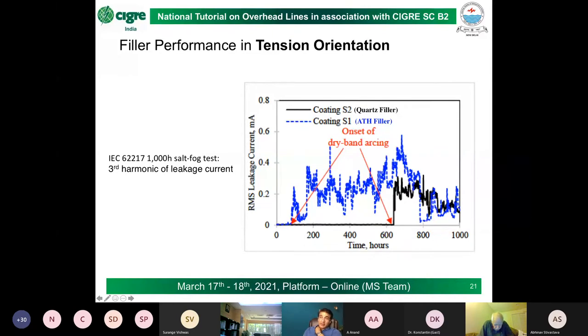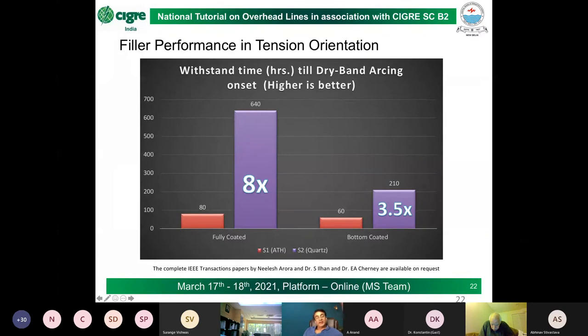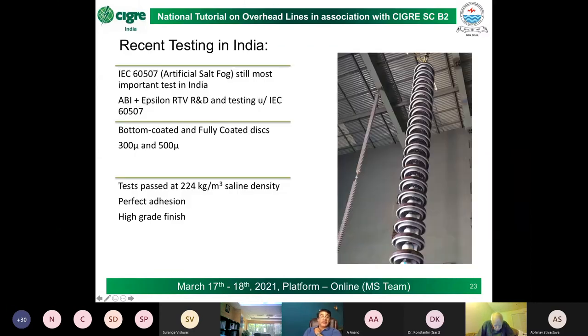If anyone is ever considering using a coating on a tension insulator, this is a key parameter to look at, because you do not want your leakage current to start really quickly, within 2 days of onset. So this is a good test. To give you an idea of how the ability of a coating in a tension orientation can delay the onset of leakage current, we look at this graph. A bigger number is better here. For a fully coated insulator, it is 8 times longer than an ATH filled one. And for just a bottom only coated, it is 3.5 times longer. It is still a very, very large number.